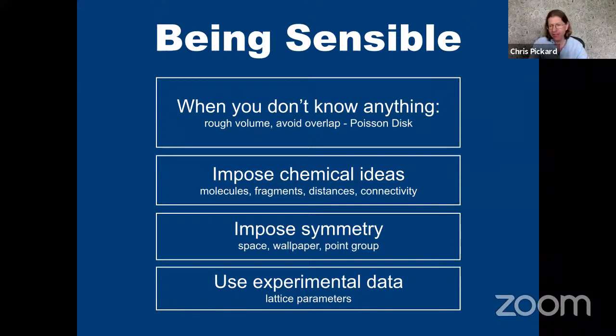Another very powerful trick is to use symmetry, because pretty much all crystal structures have at least some symmetry operations in addition to the identity. And also a very powerful approach is to team up very closely with experimentalists and use experimental data as constraints. An experimentalist might have a situation where they know the shape of a unit cell, but they don't know exactly how the atoms are arranged in that box. And actually this helps a lot. If they can give me the shape of the box, I can fix that as a constraint, as we did with the gamma boron case, and only focus on how we arrange the atoms. And that dramatically shrinks the search space that we have to explore.